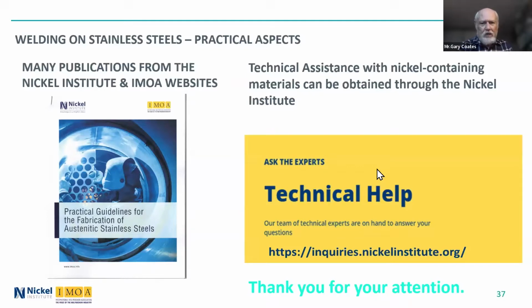What is the effect of nitrogen in stainless steel? Well, nitrogen is an austenitizer. You can divide all the elements into either ones that promote the formation of austenite and ones that promote the formation of ferrite in a weld. So nitrogen promotes the austenite phase. In typical, let's say, 304L or 316L, the nitrogen content in the base material might be somewhere around 0.04, 0.05, 0.06%. So you have nitrogen there, even if it is not reported on the mill cert, that just naturally happens.